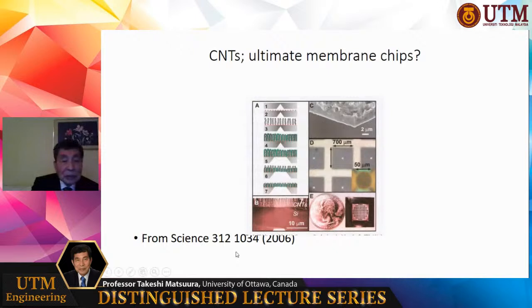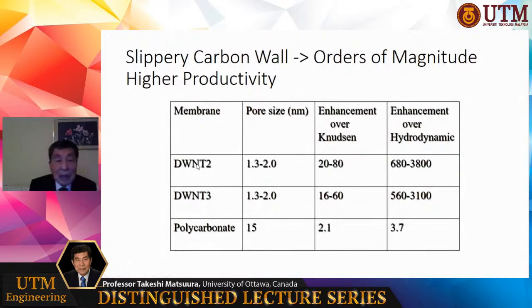This work was published in Science in 2006. It is quite some time ago already. Here, carbon nanotubes are aligned vertically. These small pieces, carbon nanotube, vertically, and this tiny membrane was constructed. And this is the size of the membrane, which is the size of the coin. And this membrane was tested for gas permeation as well as water permeation. And indeed, the productivity or the water flux was order of magnitude higher, sometimes three orders of magnitude higher than the ordinary polymeric membrane or plastic membrane.